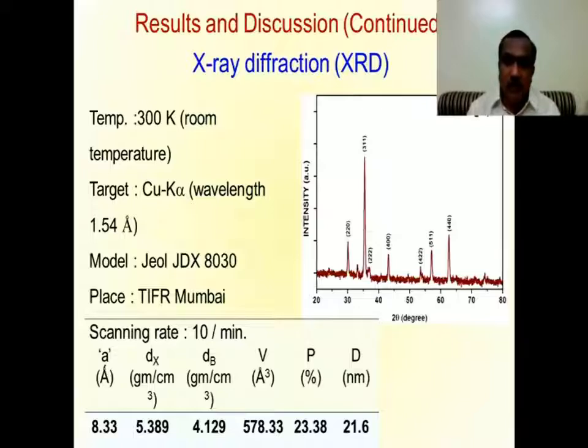There is no extra peak. All the peaks belong to the cubic spinel structure. The XRD was taken at room temperature. The target used was copper K-alpha radiation. The model was JEOL and it was recorded at TIFR, Mumbai. Using this XRD pattern, it was clear that the prepared nanoparticles are single phase, and that was our only objective, to show that the preparation was achieved in a successful way.